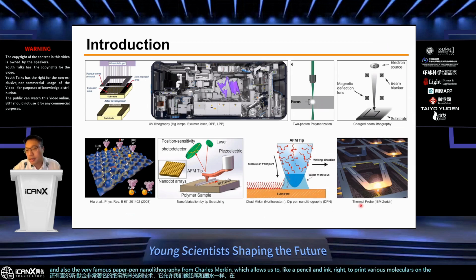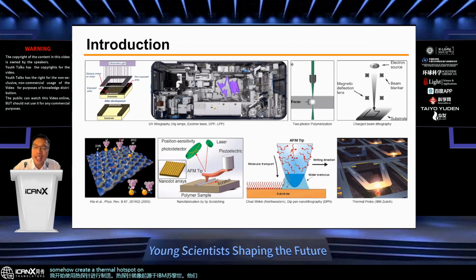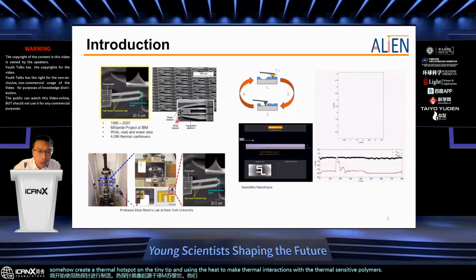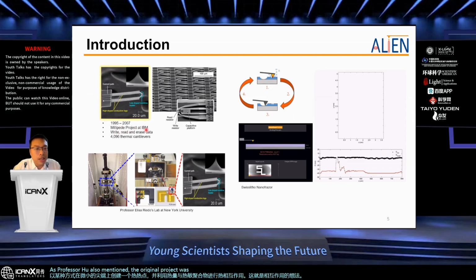And I started fabrication using the thermal probe. The thermal probe originated from IBM Zurich. They create a thermal hotspot on the tiny tip and use the heat to make thermal interactions with the thermal sensitive polymers. So that's the idea of interactions. As Professor Hu also mentioned, the original project was called the Millipede project at IBM. It was supposed to be an industrial project targeting data storage, competing with flash memory. The resolution side, or reading part, is pretty amazing.